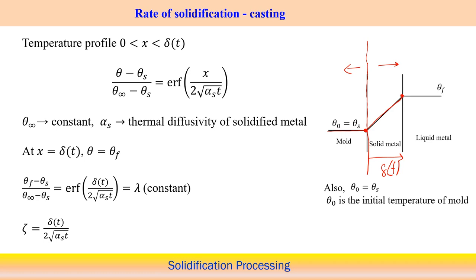Now at x equal to delta t, x being the variable, the temperature equals theta f. If we put it in, we get theta f minus theta s divided by theta infinity minus theta s equals error function of x equal to delta t over twice root of alpha s into t. These are more or less constant terms, and we can consider this as a constant lambda. Then we define zeta equal to delta t divided by twice root of alpha s into t. So another constant term, a variable, we introduce here in terms of zeta.